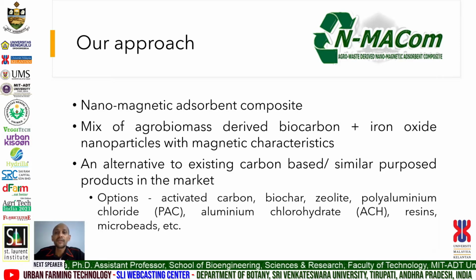The material is a combination of biocarbon generated from agrobiomass, like sugarcane bagasse and coconut shell, as the medium, which was then modified with iron oxide magnetic nanoparticles. Nanomagnetic adsorbent composite, or NMACOM, is composed of two main components: agrobiomass-derived biocarbon, the anchor and the main bulk of the composite, complemented with iron oxide magnetic nanoparticles. The attachment of the iron oxide magnetic nanoparticles gives rise to the functional nanomagnetic adsorbent composite.